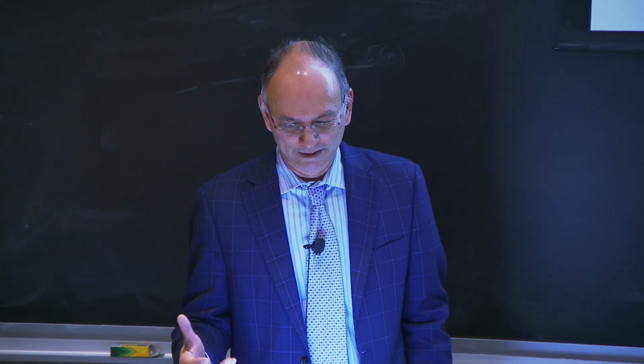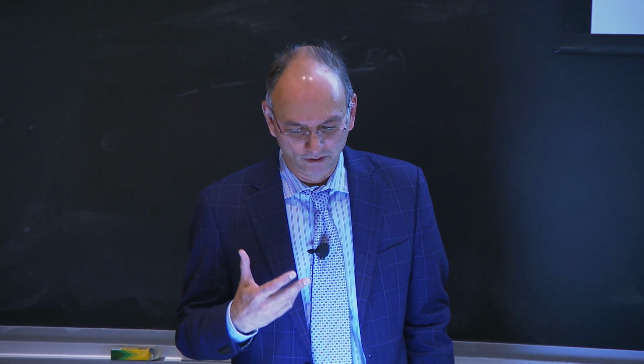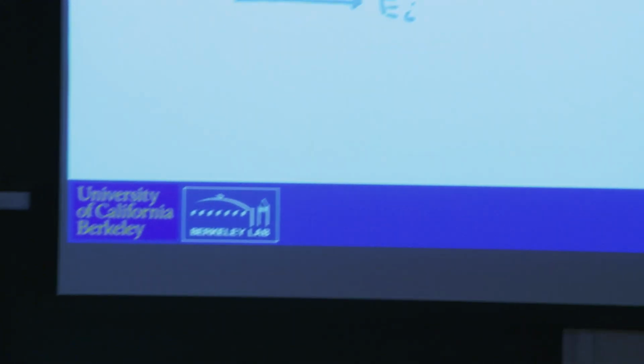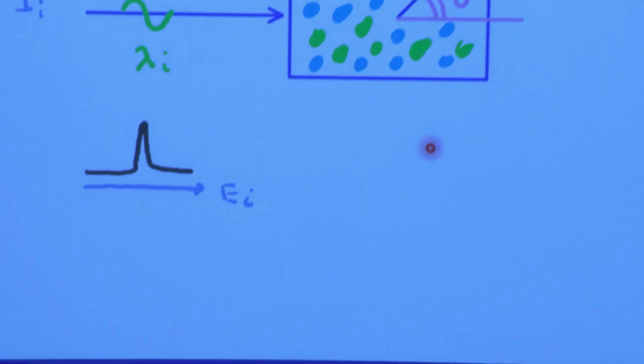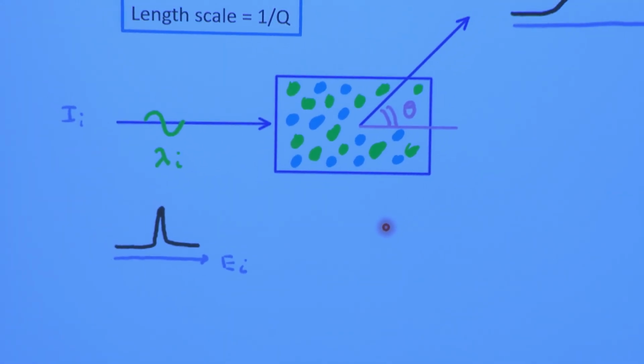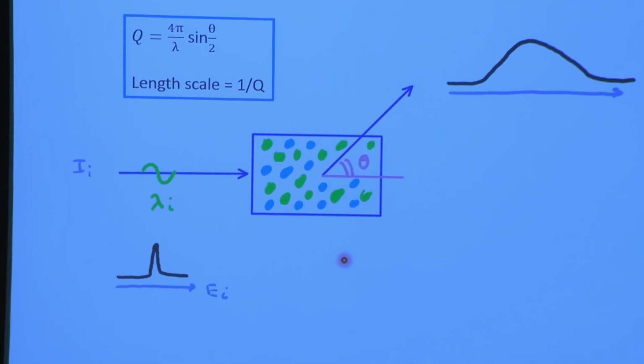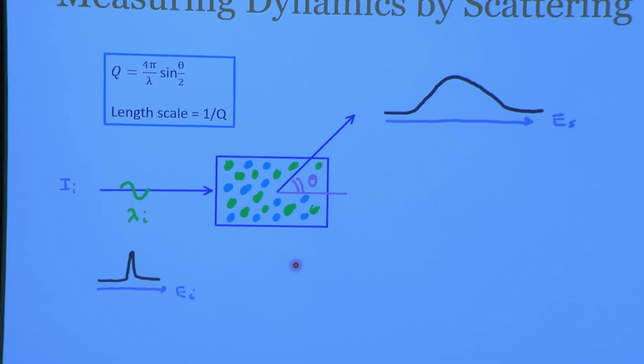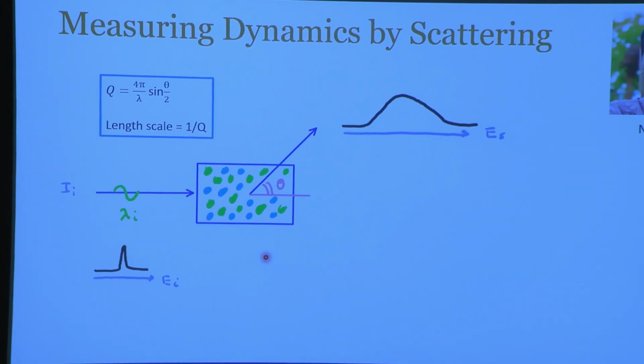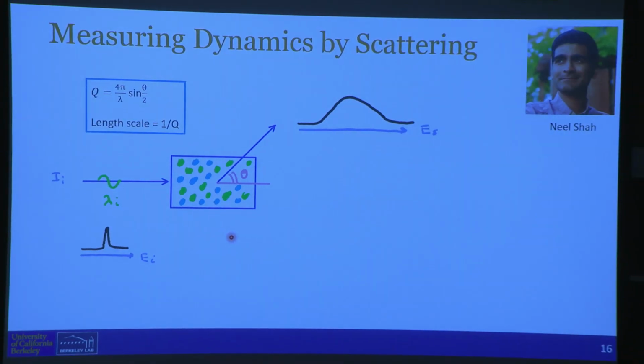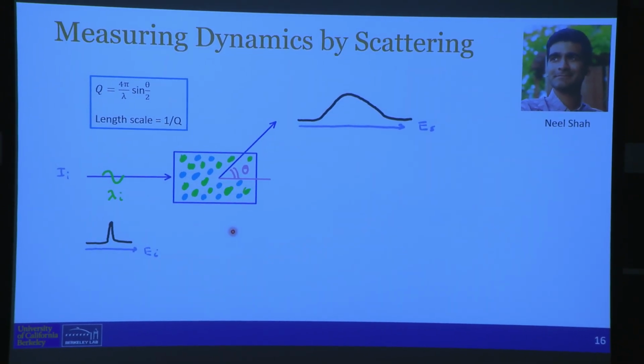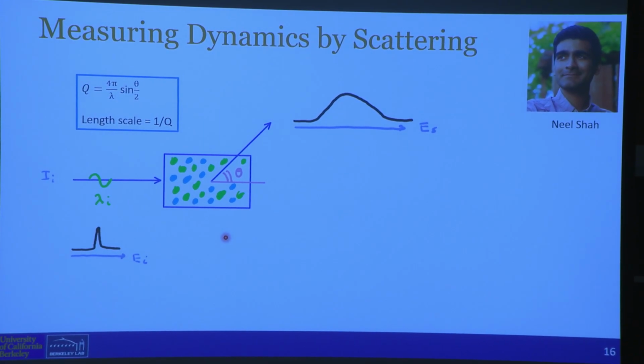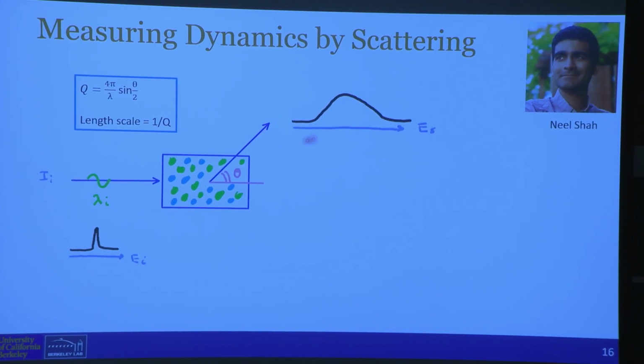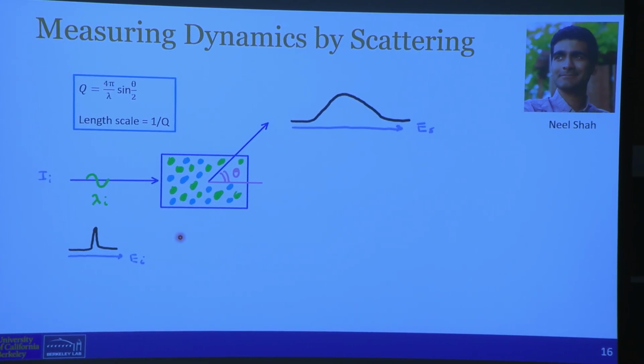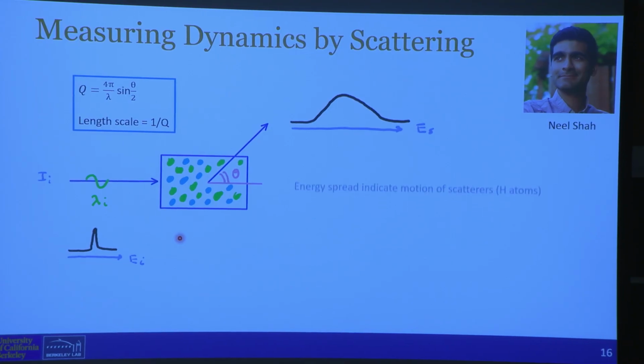We came at it from a different technique where you measure scattering and then infer dynamics. You put a beam of some wavelength lambda into your system. These things are jiggling around. And what happens is that the energy, which is tightly controlled in the beginning, is spread because of the motion of the stuff in the scattering volume. And the energy spreads. So by measuring the spread of the energy, you can get some indication of what the motion in your system looks like.